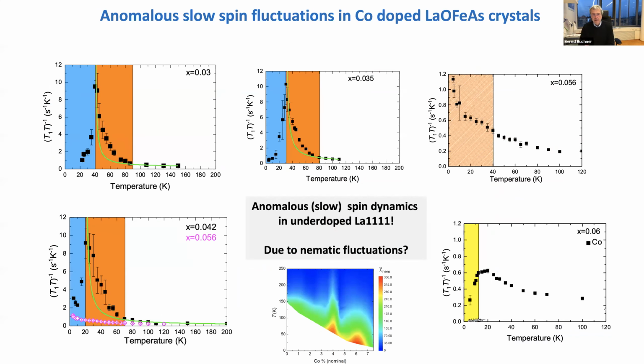That's a comparison with a compound which still shows magnetic order. We have this strong enhancement, this strong peak, which you expect at the magnetic ordering. And then we have this very unusual behavior of 1/T1T, and this is still present in the optimally doped compounds, the compounds showing the highest Tc. There we also have this very unusual behavior of 1/T1T, telling you that at least this whole underdoped region is a very unusual material.